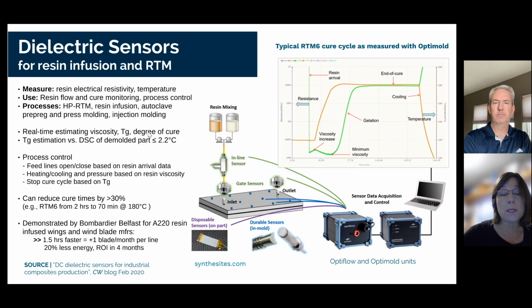In some of the experiments that Synthesites has done, it was able to compare its estimation versus the DSC on demolded samples and parts. And DSC is just one of the common lab techniques we use to make sure a part's cured or resin is cured. And what they were able to find is that the delta T, the difference, is less than 2 degrees Celsius, about 2 degrees, which is pretty impressive. So this real-time estimation works, right? They're pretty accurate with it. And they've been able to show that they can open and close feed lines, that they can stop the cure cycle based on what they're doing with this Tg estimation and degree of cure.